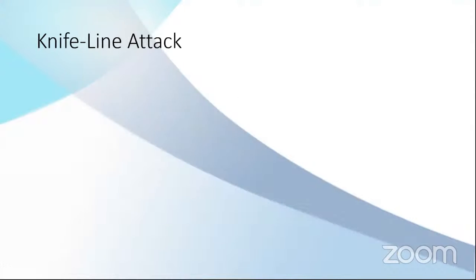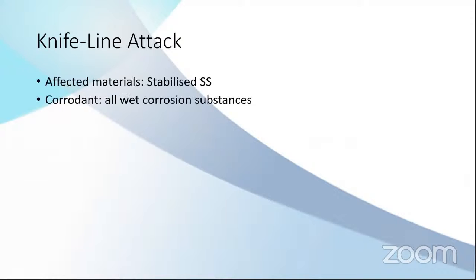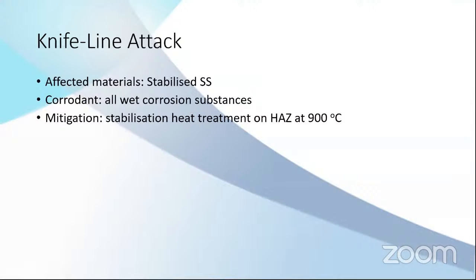And this is knife line attack. It is similar to sensitization, but the affected materials are stabilized stainless steel with niobium and titanium. So, I repeat again, they are using titanium and niobium to take the carbons, so that they don't react with the chromium. And it's the same when you have knife line attack. It seems like sensitization. So all the corrosion products can corrode the material. The mitigation is to heat treat again the heat affected zone at 900 Celsius. So this is very similar to sensitization.